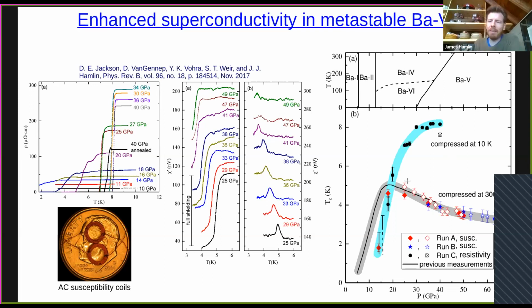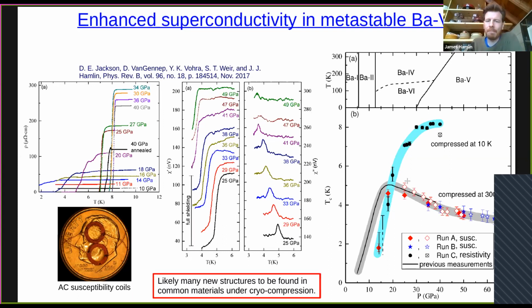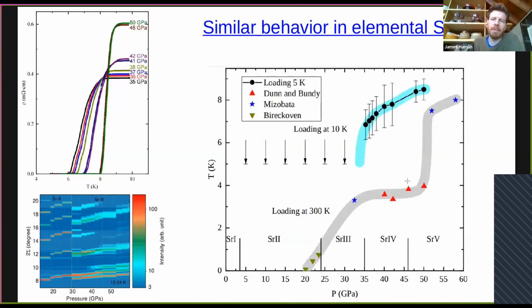And so, of course, 8 Kelvin is nothing particularly exciting, but what this shows is that cryogenic compression has some potential to find new superconducting phases. And in fact, the very next sample we studied using this approach exhibited quite similar behavior. So this is strontium, which we've just performed some X-ray diffraction measurements on. But essentially here we find the blue curve being our data obtained by cryogenic compression, substantially enhanced TC over this strontium-4 previously observed critical temperature.